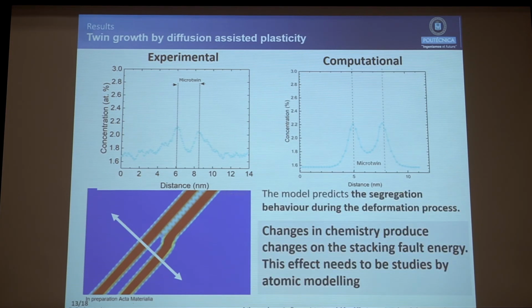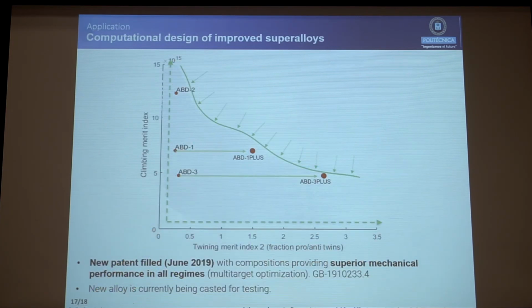So we have used this diffusional model that depends on the chemistry to try to, it doesn't show much, but basically all these are points of alloys that we have simulated in the computer, and we have taken basically the rate of microtwinning and also the rate of climbing, which is the mechanism that is happening at high temperatures. And these two mechanisms are the limiting processes for designing a new alloy.